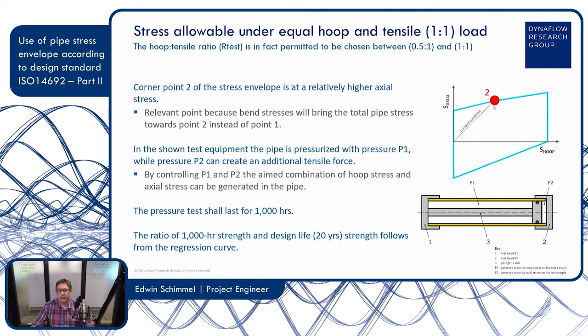This load condition is not easily achieved, but you can achieve it with this test equipment. Here we see with yellow a pipe, and it has two end caps. Now in this case from steel, that can be. Here is the second end cap. And inside the pipe, we put a pressure P1. So far, everything is normal, and that's how we always do the pressure test. But the difference is now that we put a plunger in the pipe. And this plunger here seals this area from the remaining area of the pipe.